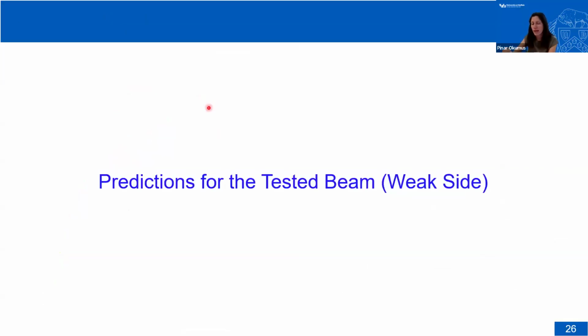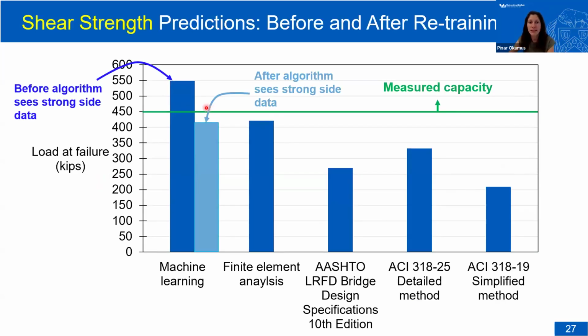Okay, now that we add this new data, I'm going to show you first the predictions for that one tested beam. So how the machine learning is doing for that single beam, and then we'll look at the overall performance. For that one single beam, you have already seen those dark blue bars. This dark blue bar was before the algorithm saw the strong side data. So again, a very similar beam, but different reinforcing ratio. And then after we retrained it with similar data, it actually got closer to the measured capacity.